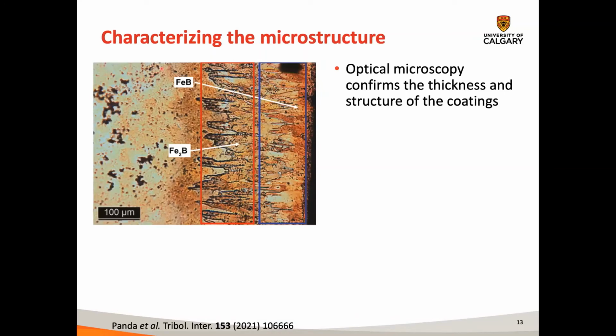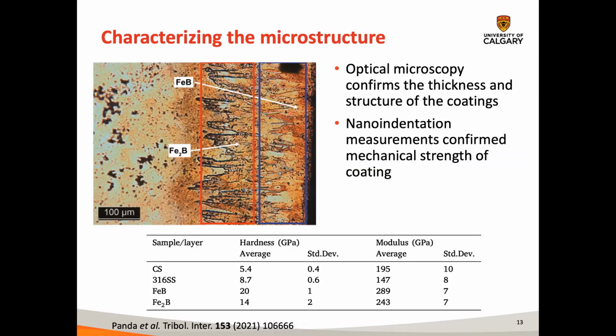So here on the left, we have the base steel. When you do this boronizing process, you get 2 different kinds of iron boride. So one is Fe2B and one is FeB. They have a slightly different microstructure and they have different mechanical properties. And so we have a nano indenter, and so we can track the mechanical properties from the bulk of the substrate all the way to the surface.